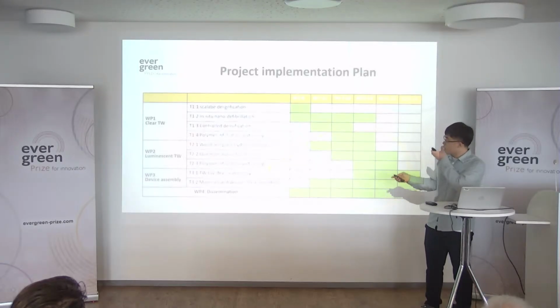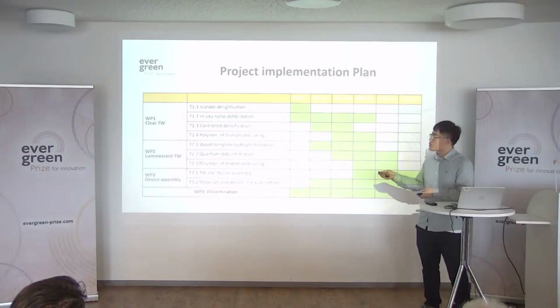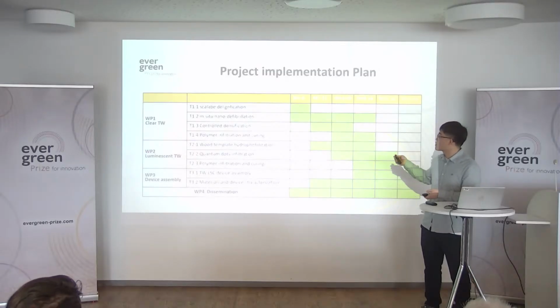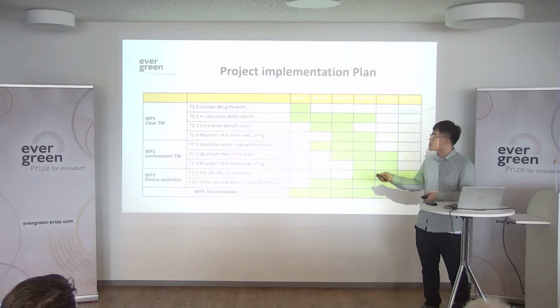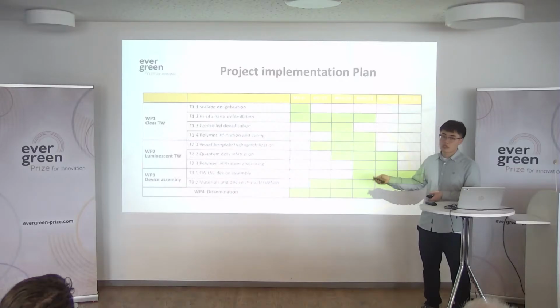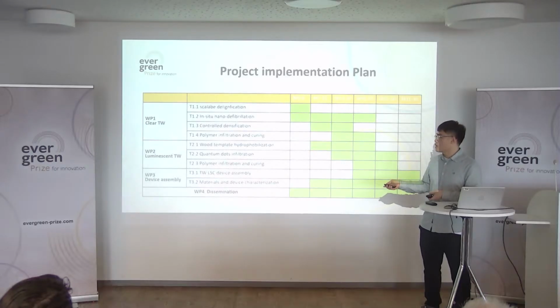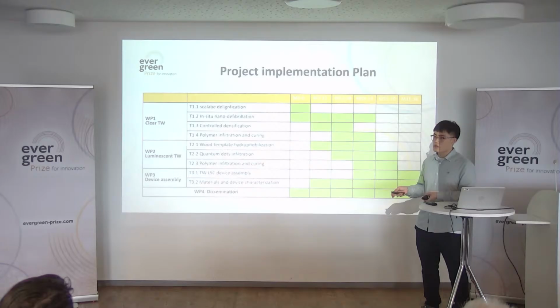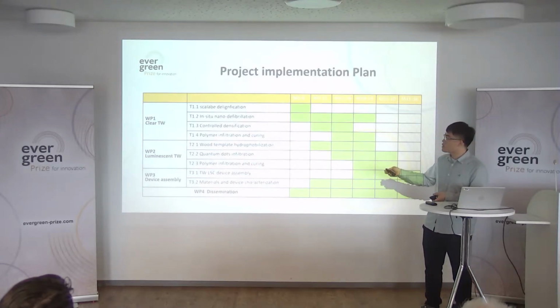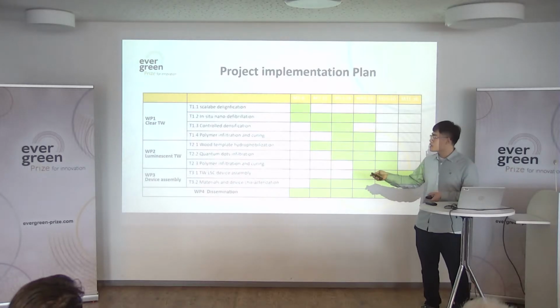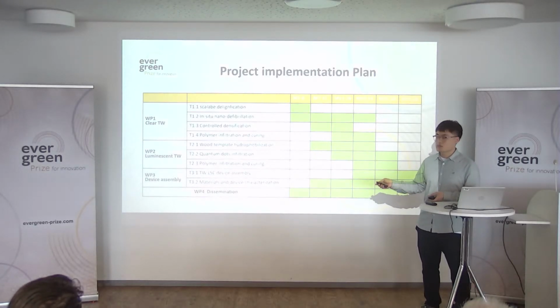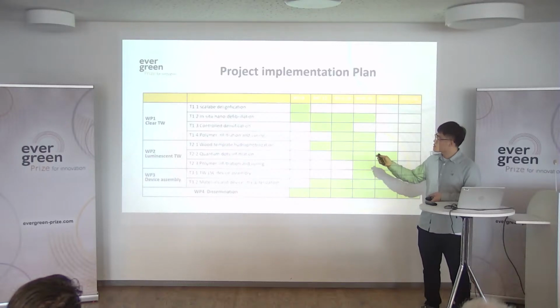And here is the project plan we designed. The first work package is the fabrication of the clear transparent wood. It will run from month 1 until month 24. Work package 1 includes the scalable delignification, the in situ nano-defibrillation, controlled densification, and the polymer infiltration and curing. Among them, the focus is the in situ nano-defibrillation, and it will take almost 2 years. After that, work package 2, the fabrication of the luminescent transparent wood, will start from about month 7 to month 30. It will include the wood template hydrophobization and the quantum dot infiltration, and also the polymer infiltration. And the first and the second are equally important for this step.